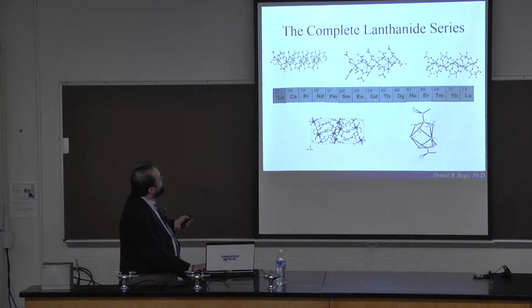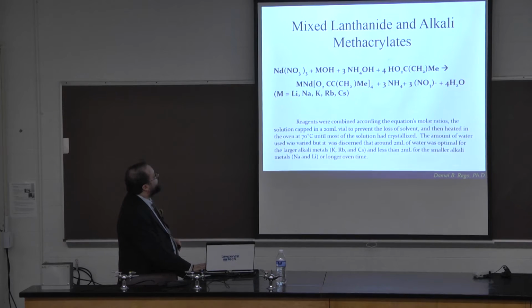And then just another view of the 9, 8, 7 coordinate, mixed coordinate, and this is actually a computational structure for promethium, which we determined that the lowest level would be 9 coordinate rather than the 8 coordinate. So we can see 9 to 8, 8 to 7, with the variable holmium and erbium.